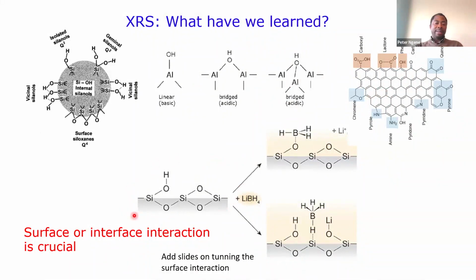And this is basically what we think is happening. So we have the silica surface or any of the oxide surfaces, and then when we add lithium borohydride or any of our active material, electrolytes, there's some kind of interface reaction that gives rise to either this or this. We are still trying to probe the exact composition of this interface, the exact phase that is giving rise to this high ionic conductivity.